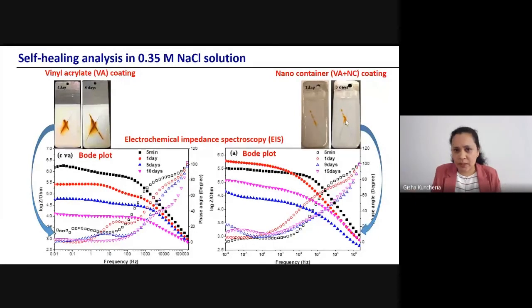Regarding the purpose of the nano containers, I explained in the beginning slide, when micro or nano cracks form, at that point these nano containers will be active and stop the corrosion. If the crack is big in size, the nano containers won't be that effective. That's the reason. So the performance of the coating that we analyzed using electrochemical impedance spectroscopy, EIS.